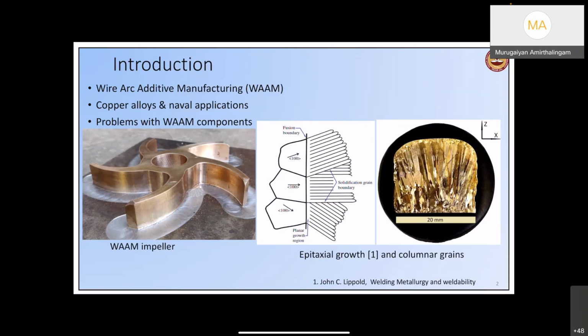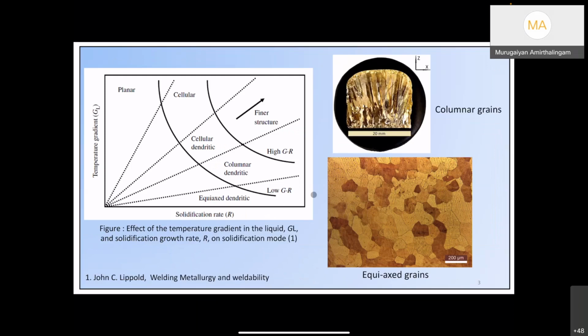So now if you deposit just like that and then use that component, it's going to crack, because conventionally these impellers are made using forging. The forged component would possess an equiaxed microstructure, the microstructure I show over here. This is a microstructure that is not a forged microstructure. It is an additively manufactured microstructure. By doing some tricks, we can also get such a microstructure.